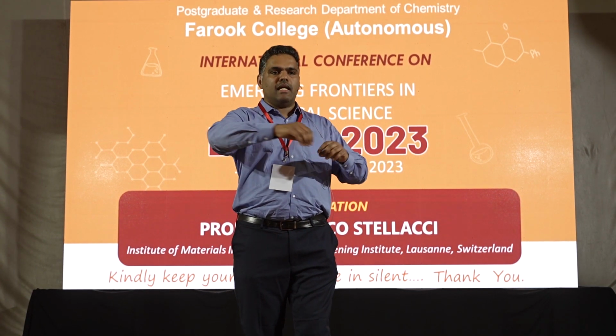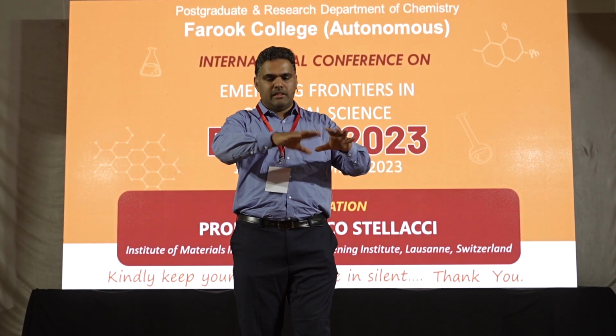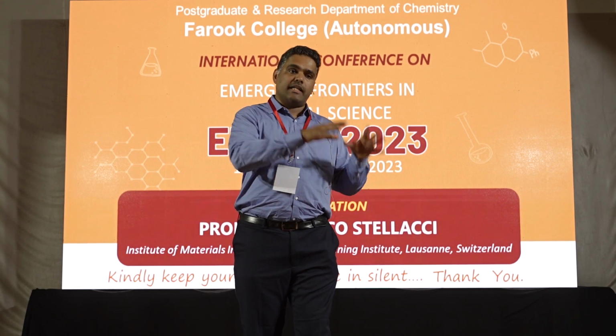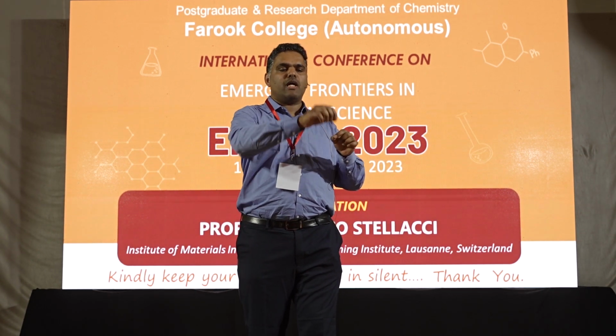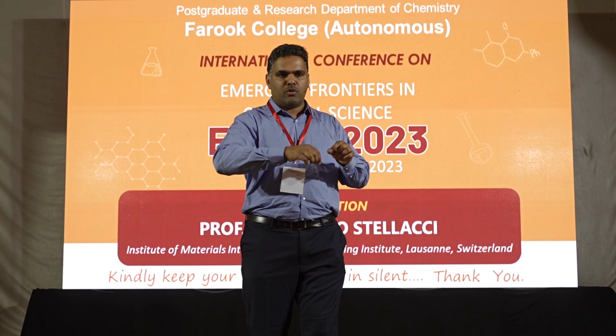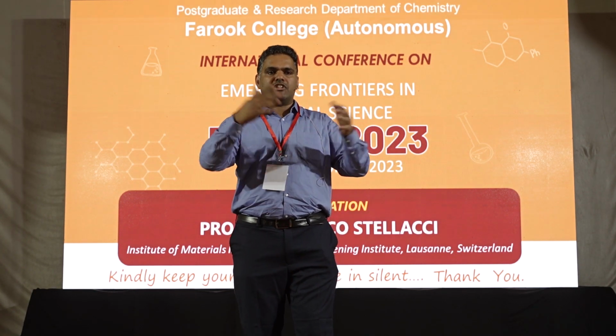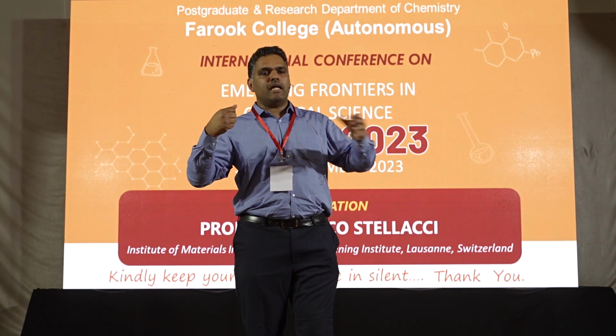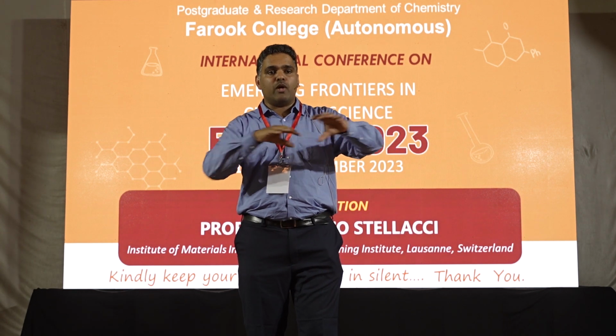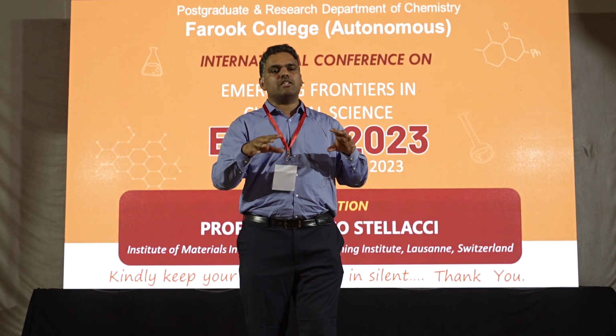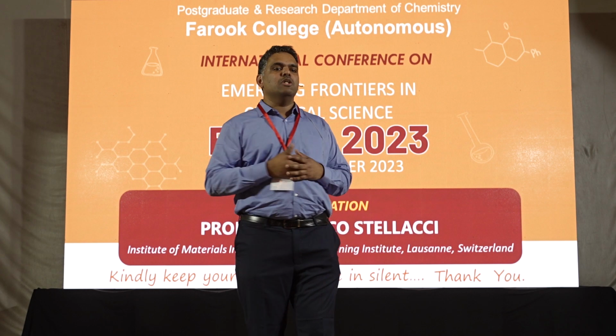They cannot form a nice layered, crystalline structure, but water can, because one water molecule can bond with the next water molecule by hydrogen bonding and form a layer of water. It's like a train. You push from the bottom side, and every compartment will move if you have an ordered structure. If you have a disordered structure, you will not get such fast movement of water.